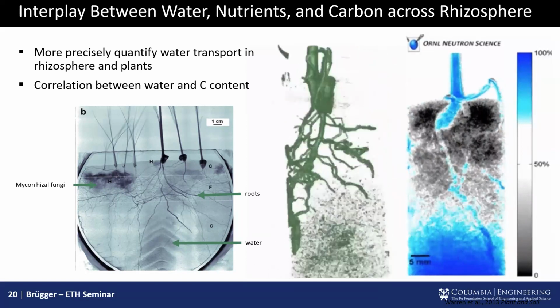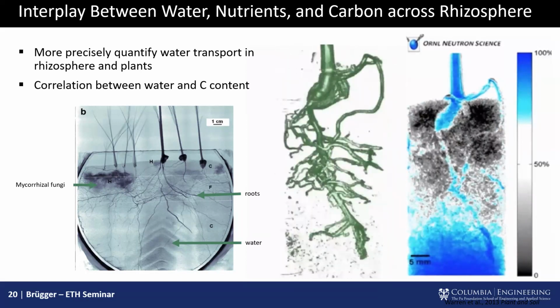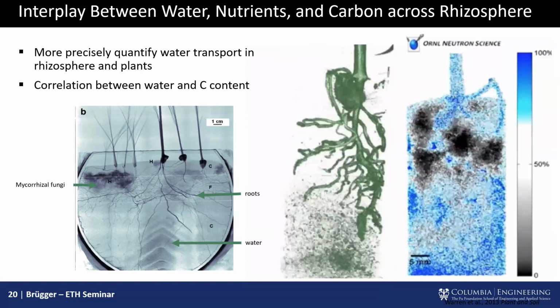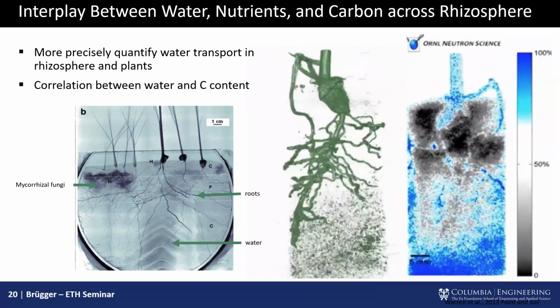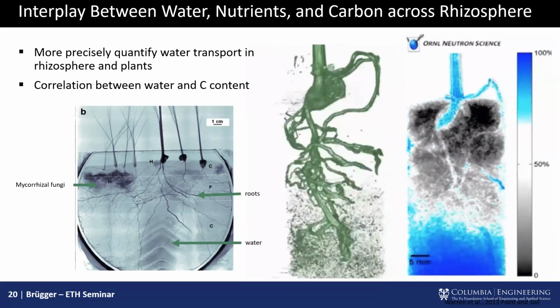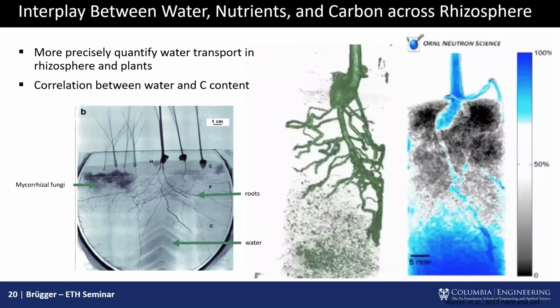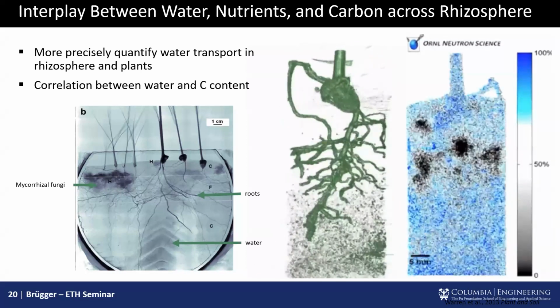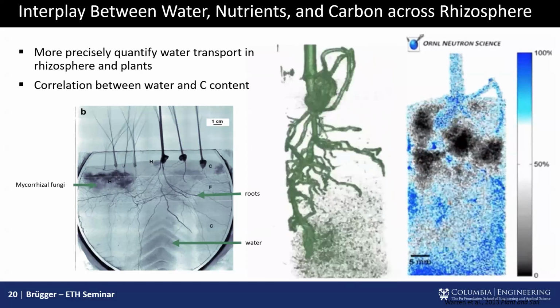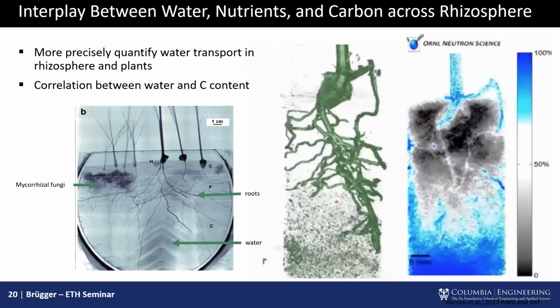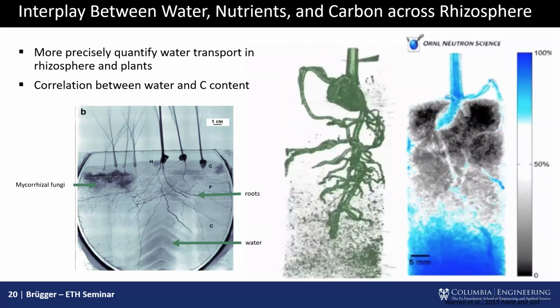So the idea with especially CUPI²D, my beamline, is to take that exposure length, that one photo, one radiograph, down to seconds. Right now, that's minutes or sometimes hours for weaker sources. But if we can get it down to seconds, then we can look at really actual dynamic results. But if you don't care about the dynamics, but something slow, it's already configured to do that. So the only question is, can you afford the beam?